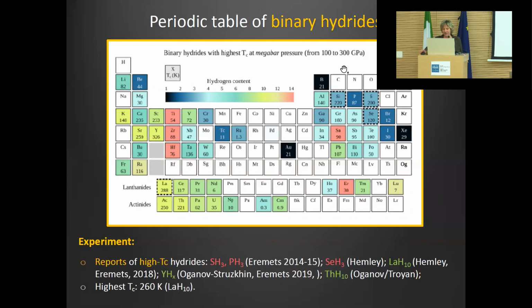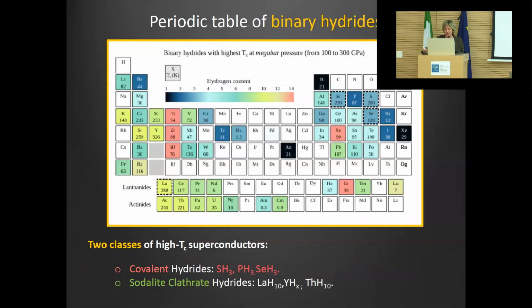Red high TC superconductors are those which appear in the right part of the periodic table. These are the so-called covalent hydrides, like SH3 or selenium H3. And then you have a whole class of hydrides on the left part of the periodic table, with lanthanides and actinides. These are much lighter colored, so they have a much higher hydrogen content, and typically they can have also much higher superconducting critical temperature. So what I'm going to do now is discuss the properties of these two classes of high TC superconductors. I will start from covalent hydrides and move on to sodalite clathrate hydrides.